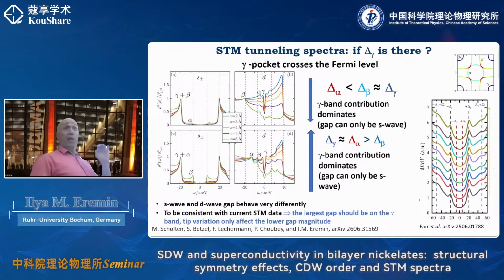Now, if we believe that the gamma pocket indeed crosses the Fermi level, like ARPES suggests, then the situation is again changing. In this case, because experiment tells you that there are only two superconducting gaps, effectively you have to assume that one of the largest gaps sits on the gamma pocket. And then the other conclusion is that you can only have an S plus minus superconducting gap, because if you put a D wave on the gamma pocket, it turns out that on average the gap will be very small. And that is why the spectra that you deduce in this case do not make any plausible comparison with experiment. So at the end, if you believe that the gamma pocket crosses the Fermi level, then the only explanation of the experimental data would be that it is an S plus minus.